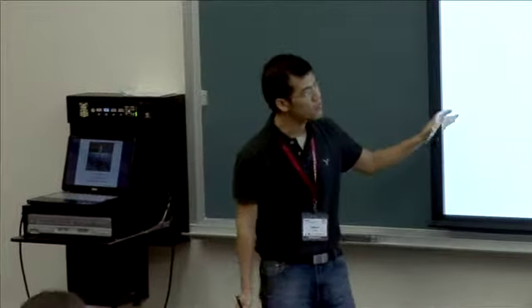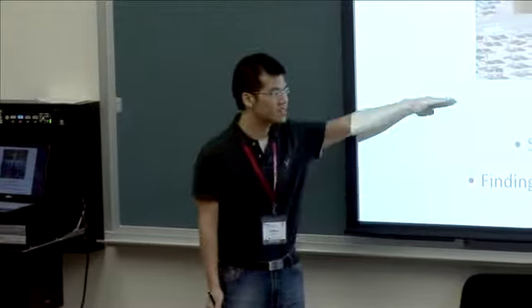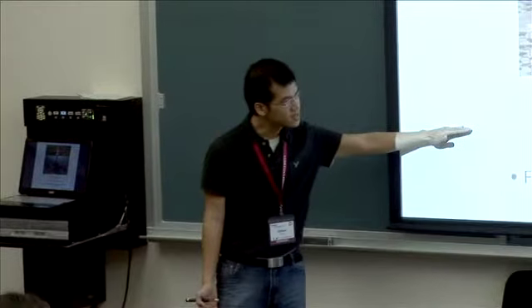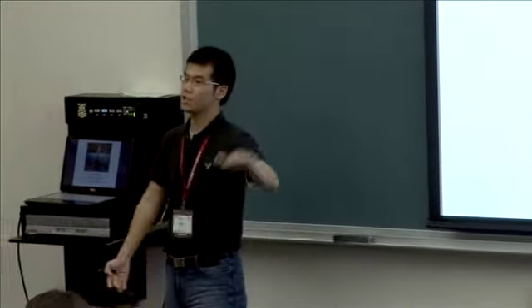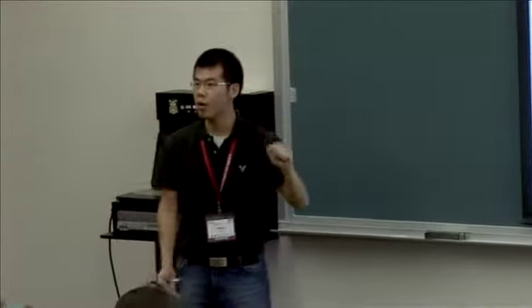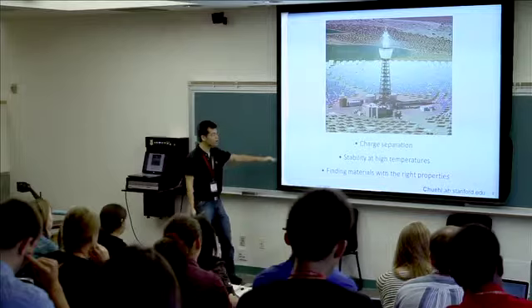But the challenges we face today are the following. Same as with a room temperature photovoltaic process, we have problems with charge separation. The carriers like to recombine, and when you go to higher temperature, the interface quality may not be as good as at low temperature, but that's one area we're looking at as to how to have good charge separation. Stability at high temperatures is another problem. When you get too high, materials tend to fall apart, and thermal expansion mismatch tends to destroy the device. So this is another challenge, but we are looking at this as well.